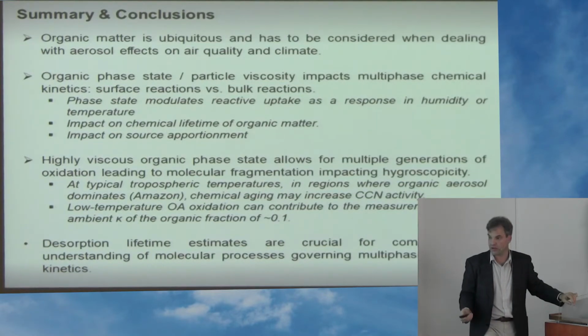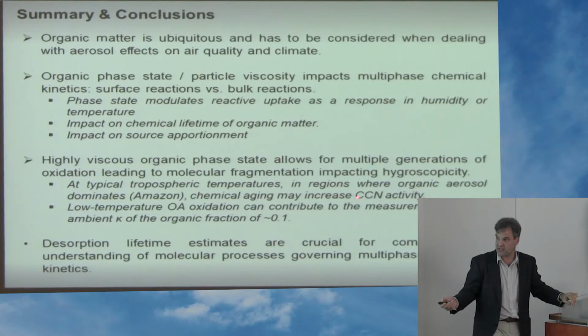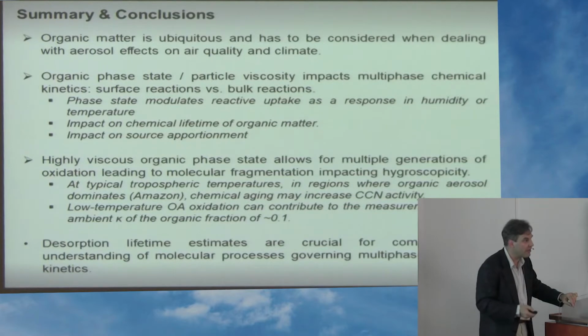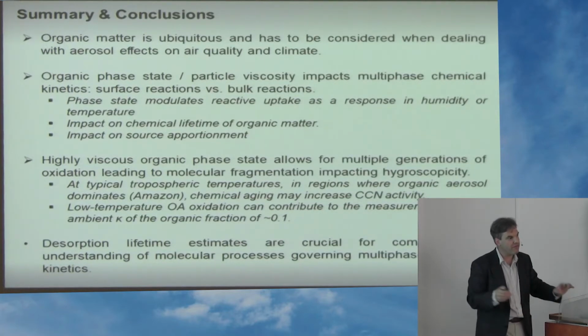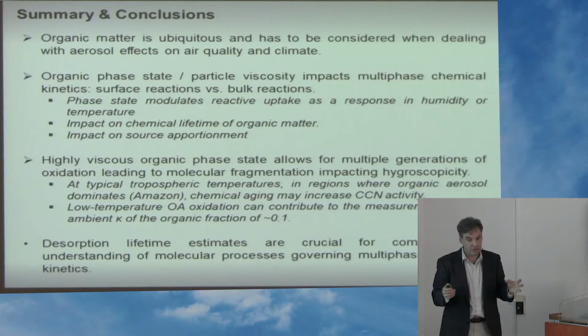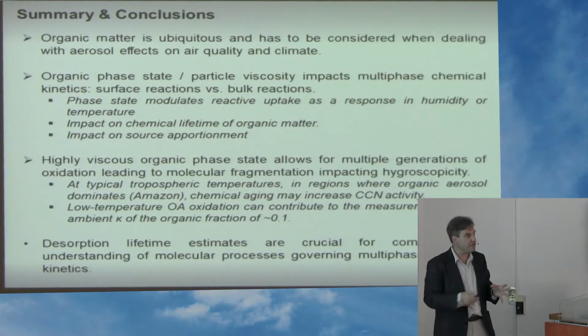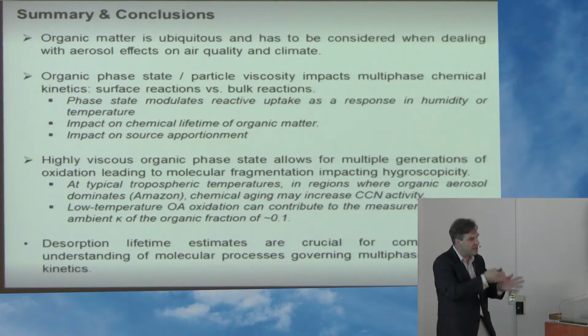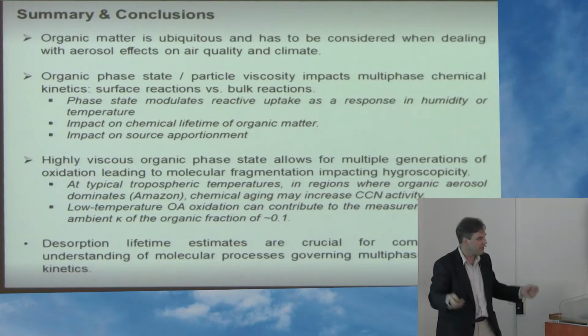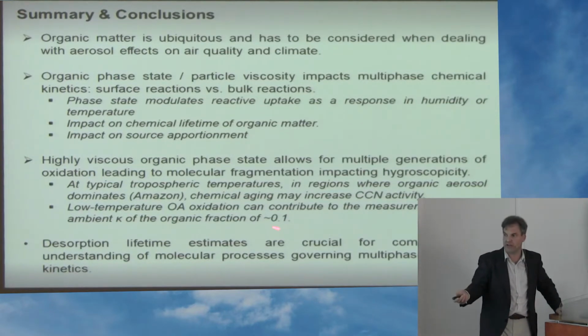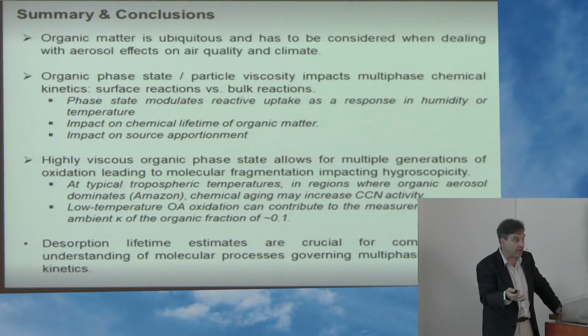What is very interesting is if you go to remote regions like the Amazon and look at the hygroscopicity of the particles there, they're all around 0.1. Even the global models show that, and no one knows why. So if you have very little sulfates, maybe this background oxidation of organic material, which I showed you enhances hygroscopicity towards 0.1, maybe that is the cause why all these organic particles end up with a hygroscopicity of 0.1.